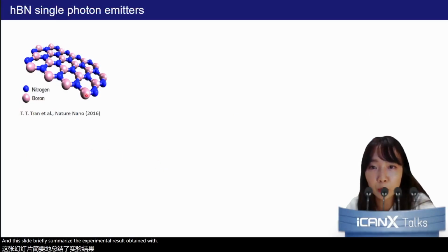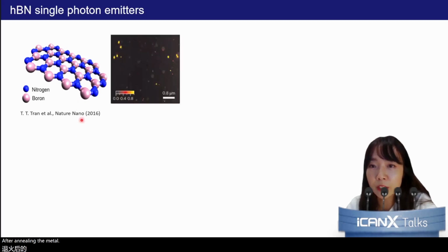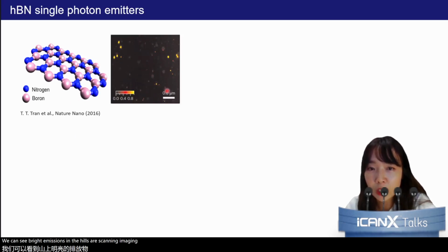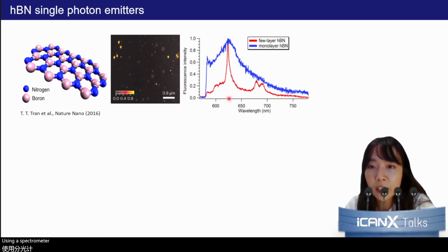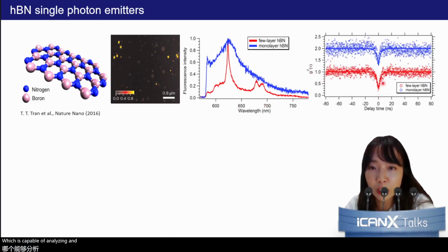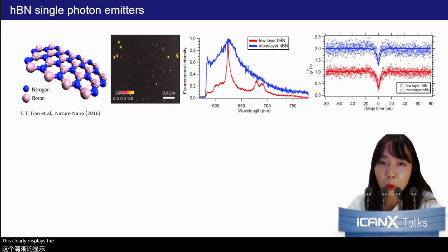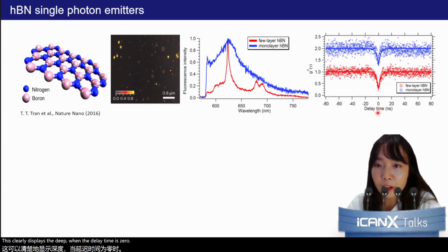This slide briefly summarizes the experimental results obtained with hexagonal boron nitride. After annealing the material at a high temperature, we can see bright emissions in this PL scanning image. Then we analyze these bright spots in further detail using a spectrometer, revealing a sharp peak around 630 nanometers. The signal here is sent to the Hanbury Brown and Twiss setup, abbreviated HBT setup, which is capable of analyzing anti-bunching of photons. This is the second order correlation graph. This clearly displays the dip when the delay time is 0, verifying the single photon nature.